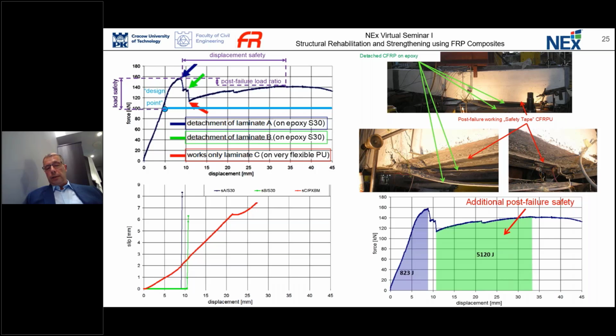What is very important in this case, if we have such a system where we are able to hang the structure, we introduce into the structure some kind of post-failure safety. This safety is measured by the energy under this curve. So if the structure has failed, if we have a flexible bonding system, in this case, we add safety to the structure in the post-failure behavior, so we allow people to escape from the structure.